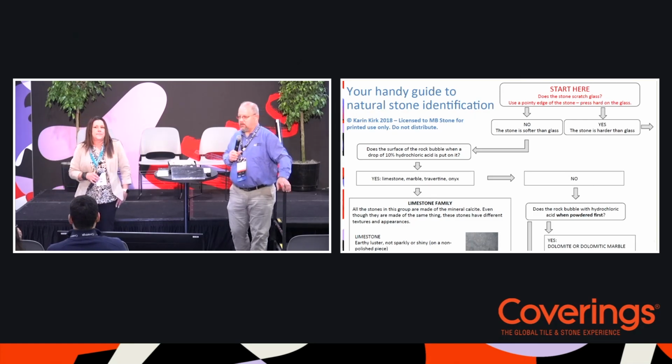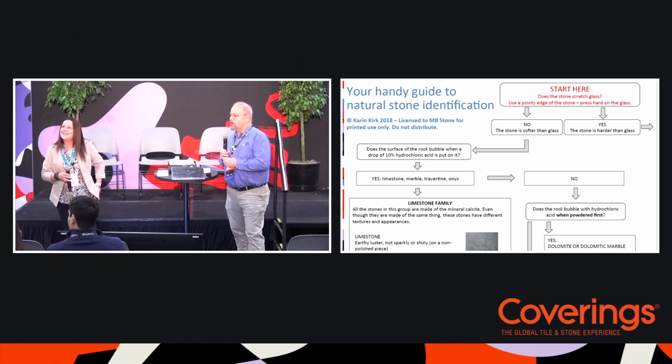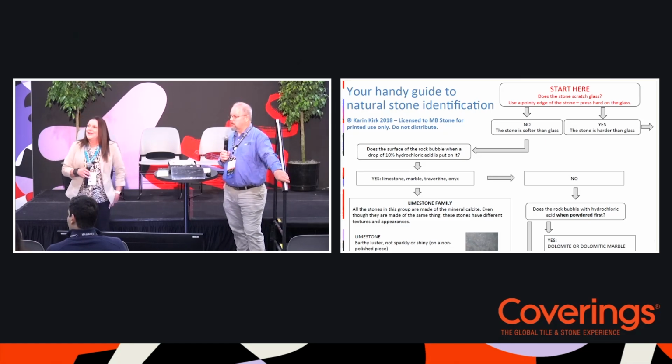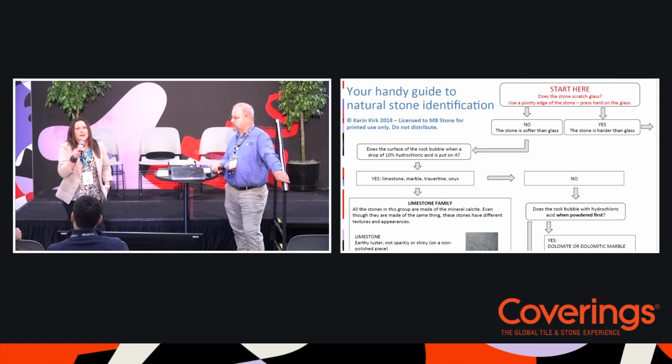Any other questions about stone? Could you elaborate a little bit more on that? Because granite that doesn't need to be sealed, what type of problems do you see in that? Sure. Like absolute black, a true absolute black, it won't absorb water, it won't absorb a staining agent, it won't absorb a sealer. So if you're putting a sealer on and you're letting it cure on the top, you've actually created more problems because the stone is tougher than that sealer you just put on. And so then you've got a sealer that can etch, that will scratch, that will discolor. So you've actually lessened the value of the stone that's underneath. And a lot of times when that sealer's removed, the stone's perfect.